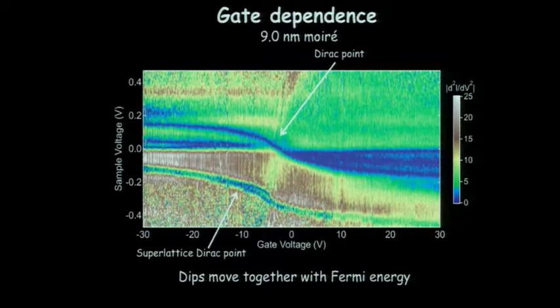And to see it a little bit more clearly, this is a color scale where the color now is the density of states as a function of gate voltage. So we're tuning the charge density in the sample. The Dirac point just moves on this square root of the gate voltage. And there's this superlattice Dirac point, which just moves parallel to it right here. And so these two are always a fixed energy apart. So that's how we know that the dips that we're seeing in this spectroscopy are actually a band structure effect and not coming from some other thing. They're moving always in parallel here.